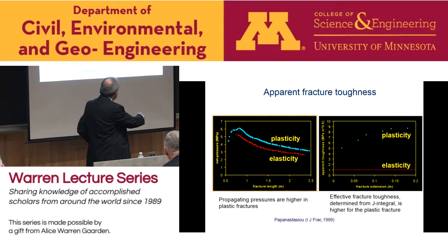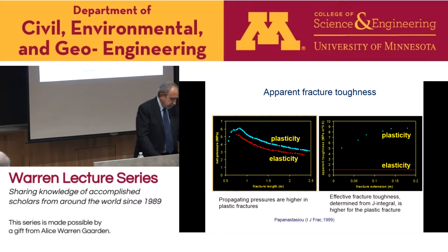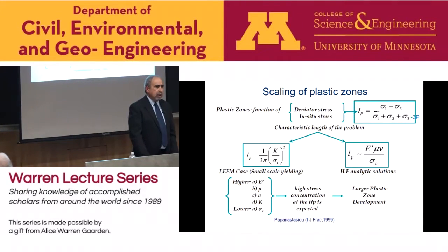With plasticity, you can see that it increases with the first propagation steps, and then it reaches a kind of asymptotic value. Here in this case, from 1, we reach a limit value around 9 megapascal square root meter. We did calculation, and we calculated apparent toughness up to more than 30 megapascal square root meters. And of course, how important is plasticity? It depends on the size of the plastic zones.